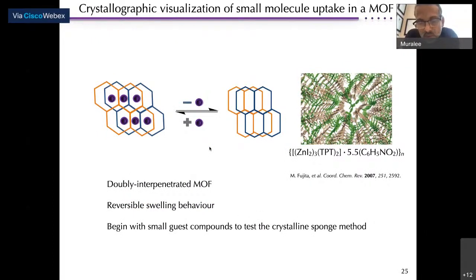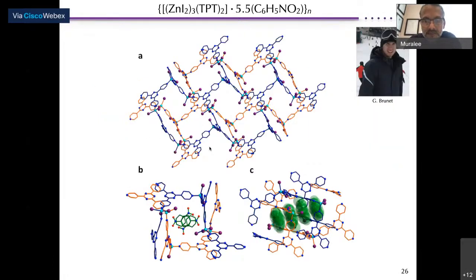So what we learned from this cobalt system, we just found out it is really difficult to work with. It is unstable. But what about the zinc system, the analogous zinc compound that Fujita reported, which is an interpenetrated framework which has a reversible swelling behaviour. That means if it is interpenetrated, you can think about the stability. Of course, it is much more stable, but also you can have this intricate framework where the pores are ideally partitioned to accommodate gas. And if you look at the channels here, in these channels, you see these nitrobenzene molecules, which is a solvent of crystallization.